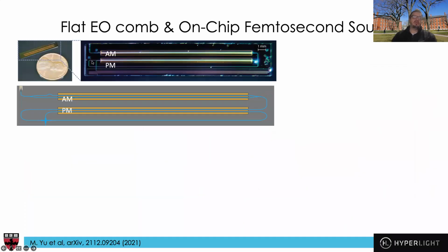And here's the solution. This is a chip that was developed in collaboration with Hyperlight that consists, as shown in this cartoon, of one amplitude modulator and a special type of phase modulator. Both modulators operate in a ground-signal-ground configuration. In this phase modulator, light is inserted from this end, goes through a Mach Zehnder interferometer, comes back here, goes through one arm of the phase modulator, and then loops back and goes through the other arm. In this case, we can make the effective length of the phase modulator twice the physical length, which reduces the V pi, which is nice.